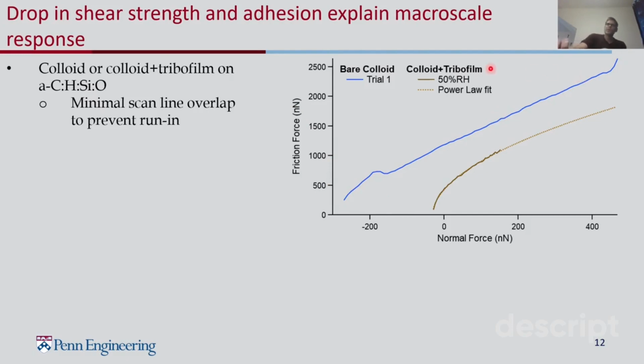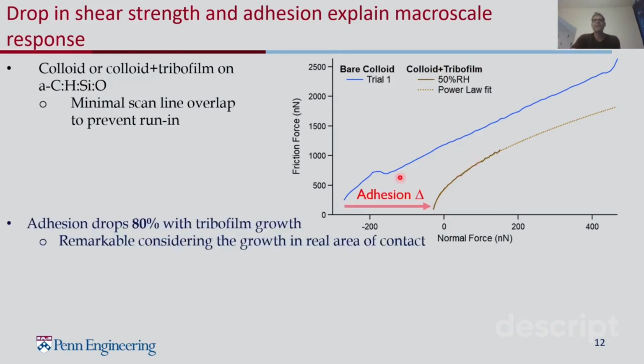And as you might expect for this multi-asperity contact, we have a linear relation between friction force and normal force. But then if we switch to the case where there's a tribofilm on the colloid, what we actually see is that there are a number of changes that occur. The first one is that there's a huge drop in the adhesion, about an 80% drop, and it's all the more dramatic considering the fact that we know that the real area of contact between the two interfaces increases tremendously. But the fact that the adhesion drops means that if you shift this curve to the right, you'll have lower friction at any given normal load. This is responsible for at least a part of the friction reduction that we see.